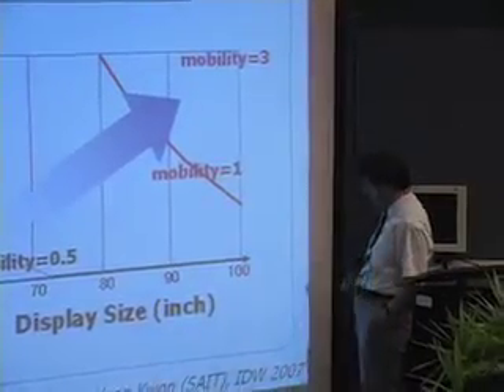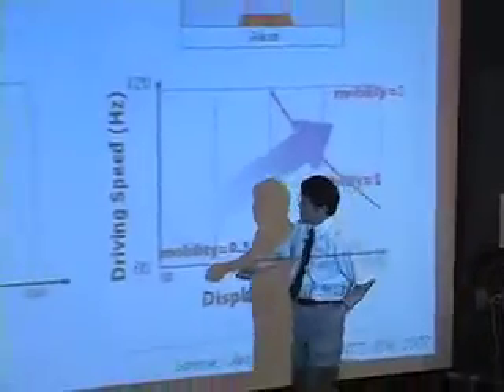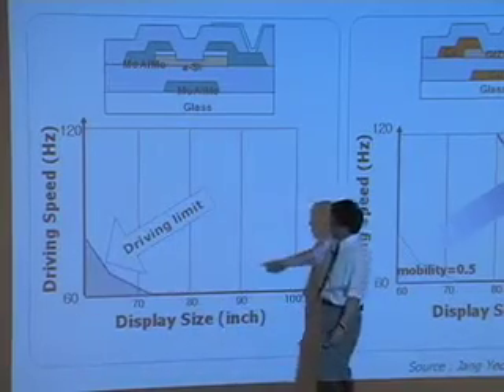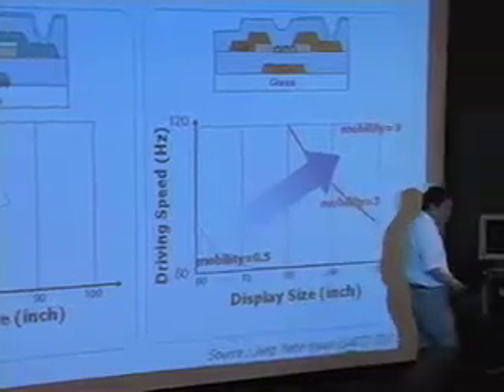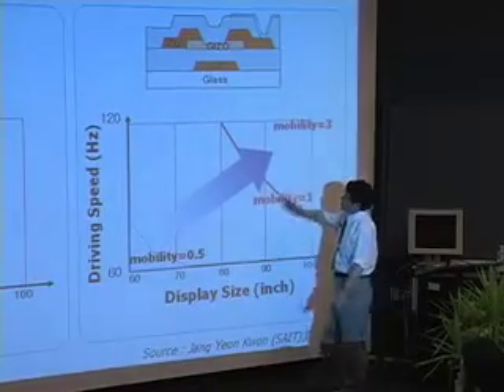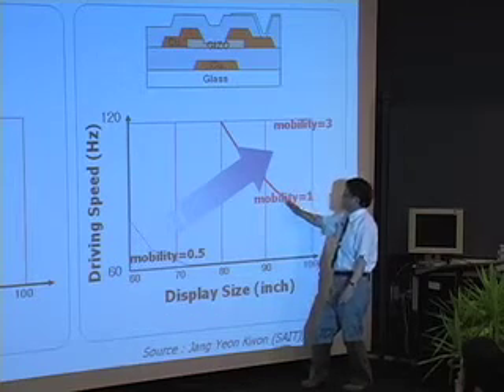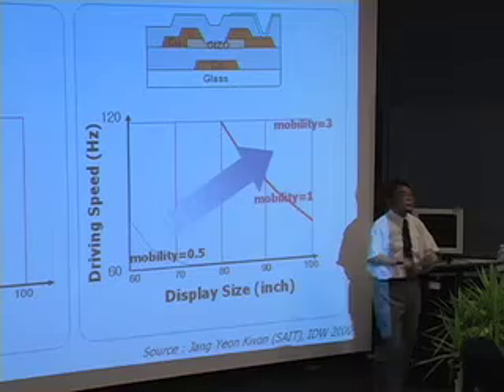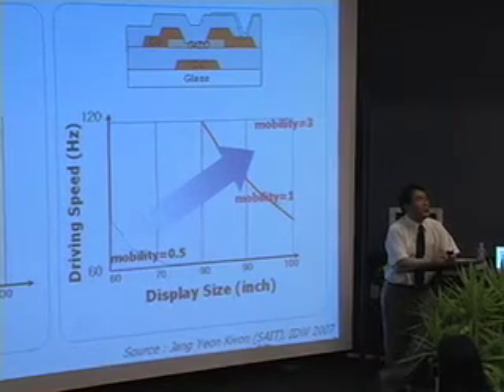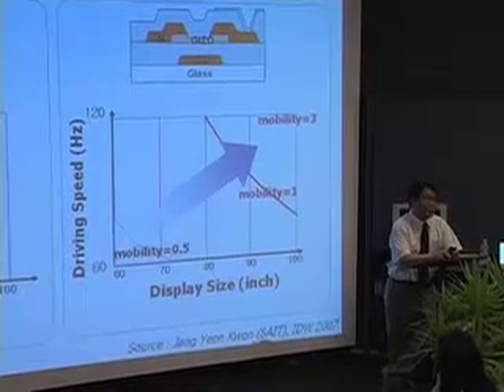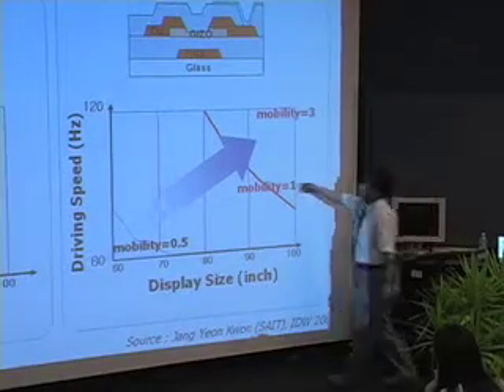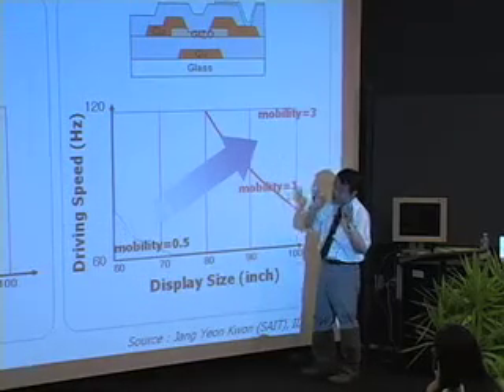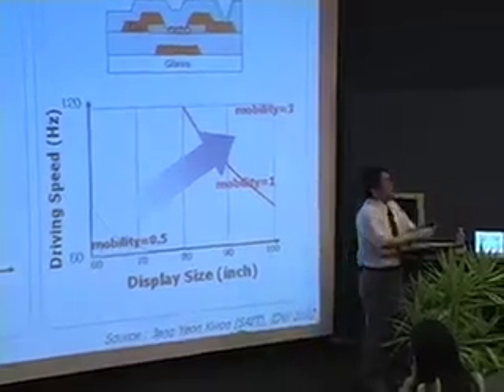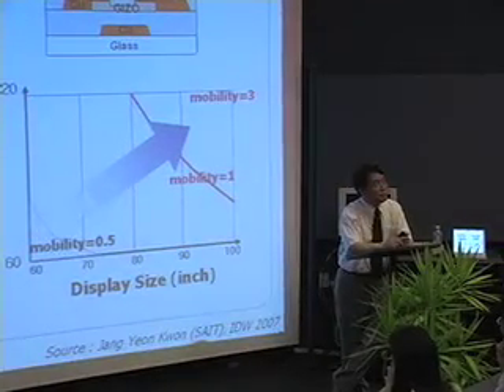This is data by Samsung Electronics. The current LCD is right here, at 60 Hertz, and the size is 70 inches. A mobility of 0.5 is enough, but as performance moves from here, a mobility of 1 or 2 is needed. Amorphous silicon is commercially available, and its mobility is 0.5. 0.1 is impossible practically. So a new type of TFT is absolutely needed to meet the new trend of the LCD. That's why the amorphous oxide TFT is now booming.